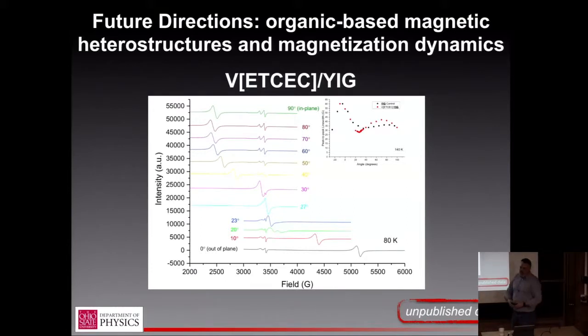The other thing to try is growing it directly on platinum and looking for some sort of inverse spin Hall signal. And there, we still could try that. I think the reason I was leaning towards this is, we've done spin pumping measurements in inorganic systems, and as I'm sure you appreciate very well, there are a lot of potential transport artifacts in that measurement. And so, famous last words, I was thinking this would be easier, at least, or less ambiguous. But none of what I'm saying is definitive. This is why it's not yet published. We're in process, but I have high hopes that we'll get there. It's just a matter of turning the crank enough times until we get the right set of conditions.